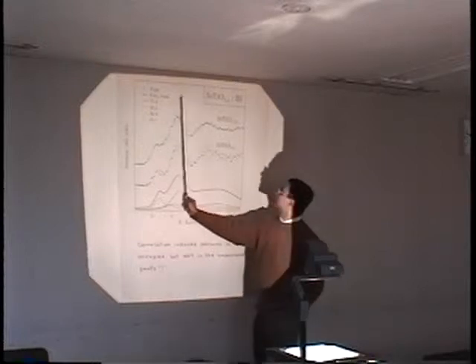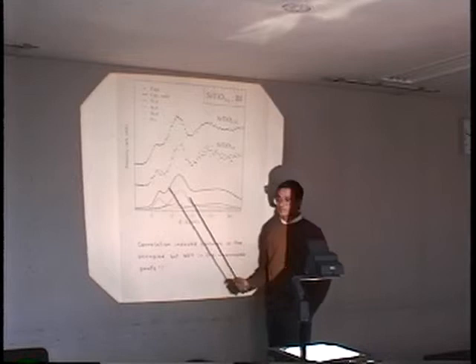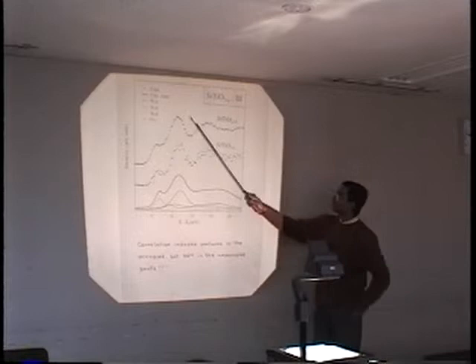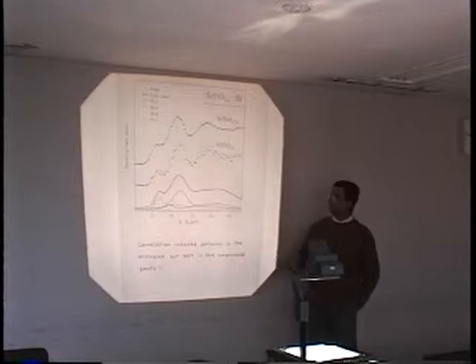There is a small shift of the peak towards the left, as one would expect if the Fermi energy moved in. Okay? And there is no sign of correlation-induced satellite here. Every feature here is explainable in terms of band structure calculation and a rigid shift of the Fermi energy.